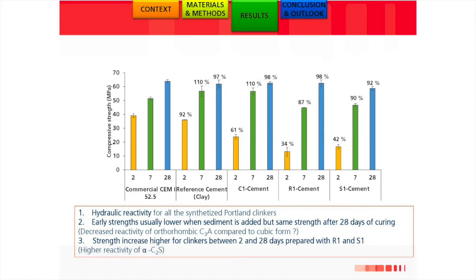But in any case, for an application in the building sector, it's interesting to look at the compressive strength of this material after 2, 7, or 28 days after setting. That's a commercial CEM I cement, without any additive, reaching about 65 megapascals at 28 days. That's the reference clay we manufactured with our quarry rocks—we obtain values fairly similar to the commercial product.